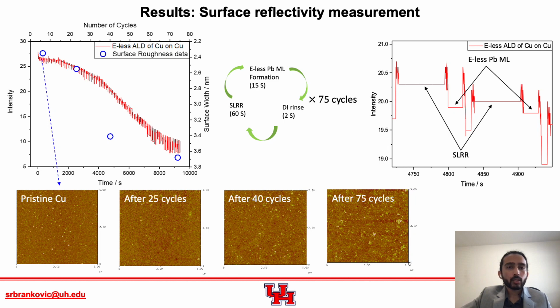Now, after development of this setup, we evaluated it with two different types of experiment. First is where we deposit copper on top of copper substrate. So we would have homoepitaxial deposition. So the protocol is that we initially form a lead monolayer on the substrate by electroless deposition for 15 seconds, and then we rinse the sample for 2 seconds. And then the next step is when the substrate is exposed to the solution which contains copper ions. So during this SLRR step for 60 seconds, copper ions would replace lead, and then we would form a copper monolayer on top of copper substrate. So this completes one cycle and it is repeated 75 times.